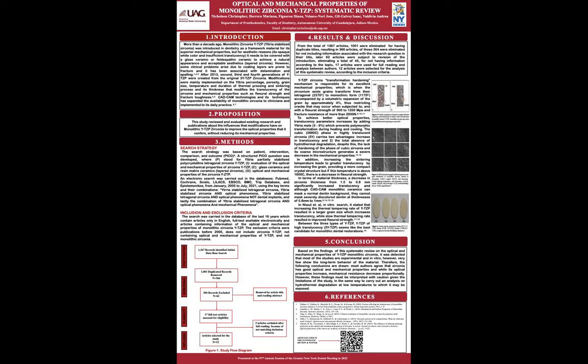Also, if we increase the sintering temperature and time and increase the thermal ramp rate, the zirconium oxide grains will acquire a larger grain size that translates to higher translucency, but there will be a proportional decrease in the flexural strength and fracture resistance. And so on with the different modifications.